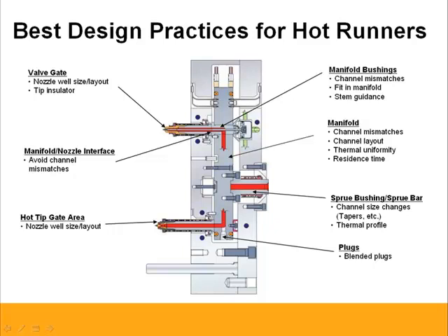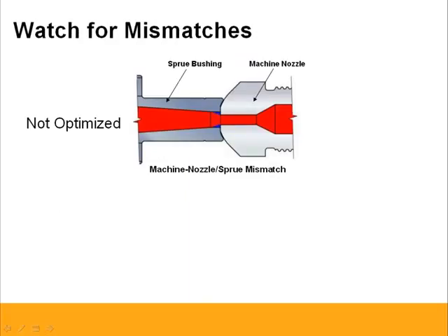So the first thing, very often overlooked, of course, everybody changes molds from one machine to the next. But one thing that I would like to point out is that it's often forgotten. It's very important that you actually match the machine nozzle orifice with the sprue bushing orifice. Often overlooked because everybody is hectic and has no time.